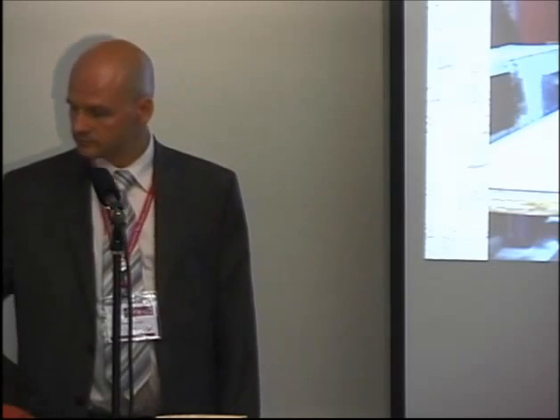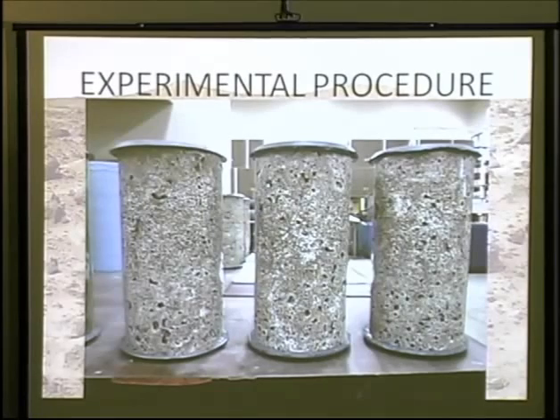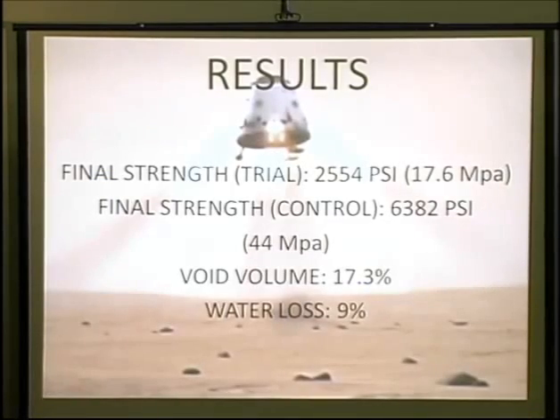Mixed it in the Martian atmosphere, it would not have had that same boil-off? Right. Like I said, if you can vibrate it, we normally use a vibrator to consolidate concrete, and that forces the air bubbles out of there. It also occurs in Portland cement concrete, but I wasn't able to do that with the equipment I had available. So these were the samples, and I had to work around the air bubbles. I'll get to how I did that. This was the final results.